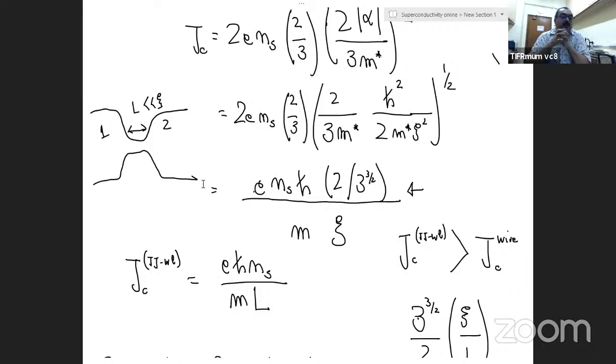Physically, how you apply the magnetic field, of course, will determine how the Josephson junction will behave. The Josephson junction will behave very differently if you put the magnetic field perpendicular to the junction or along the junction. But those matter when you solve the Josephson junction equation. I am just telling you to set up the equation. When you solve it, you have to be careful about which direction you are applying the field, not when setting it up.